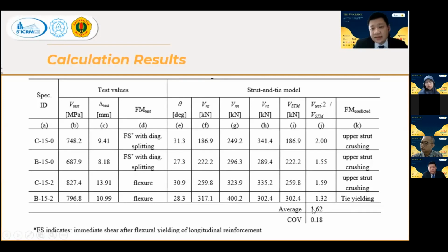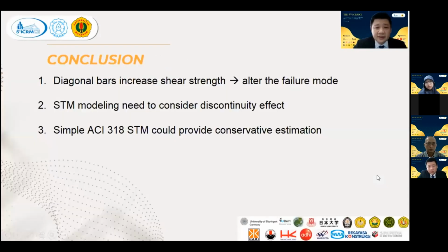And we can also see that the failure mode predicted is more or less similar with the test value. So here we have flexural shear behavior, we have the upper strut crushing. But if you have diagonal bars, then we have diagonal flexural behavior in the test. But still in the predicted value, you have the upper strut crushing and the tie yielding here. So some modifications for the strut-and-tie modeling may be needed in the future.